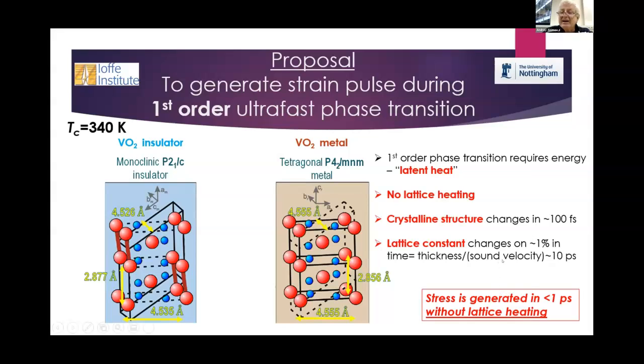But anyway, at first, how strain works - for us it's important, but at first, of course, stress is generated. The transition takes place very fast, in less than 100 femtoseconds, and then stress appears in the system and starts to work. For the elementary cell it works very fast; for the lattice constant it works longer, but we shall see how it works in practice.